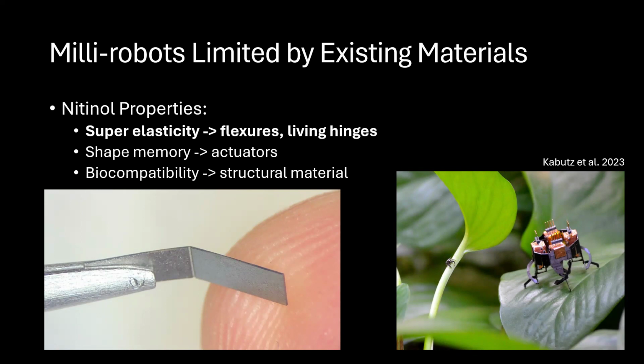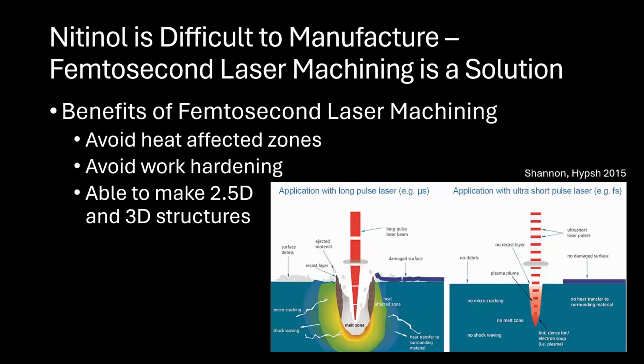By rastering away sections of nitinol, like for the hinge shown in the figure on the left, we can create monolithic, multifunctional structures, significantly reducing the manufacturing time of robots like M-Clary on the right, which is manufactured with a stack laminate process. This process requires cutting multiple materials and heat pressing them together, leading to a much longer manufacturing time than cutting from a single material.